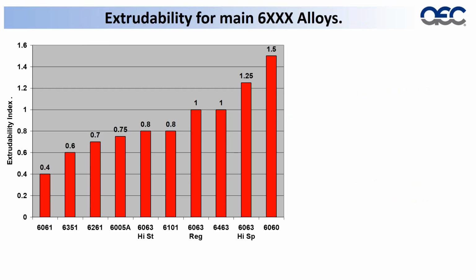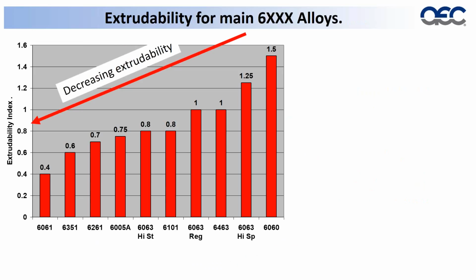The next thing that comes into play is the effect of alloys. This graph here has got the common 6000 series alloys, from 6060 on the right through to the strongest, which is 6061. In fact, there's also 6082 as a possibility. It's even slightly stronger. The thing that's important to know is as that material gets stronger, which is going left, the extrudability is decreased. And this is a big issue because, as Rick says, as end customers, what you're buying is press time. And if the extrudability is decreased, then the product per hour is reduced and you end up renting more press time. So it's a direct cost.